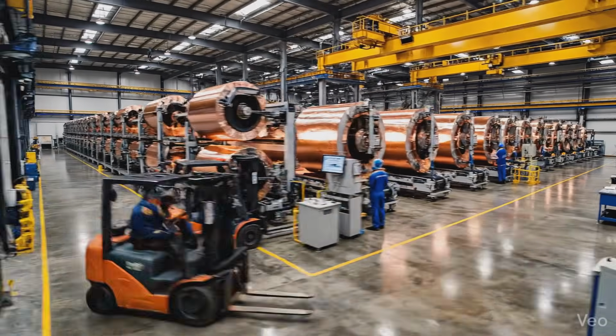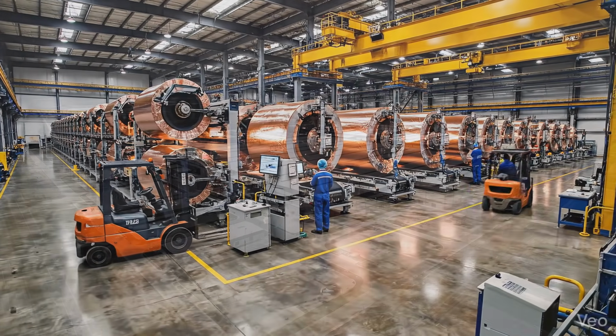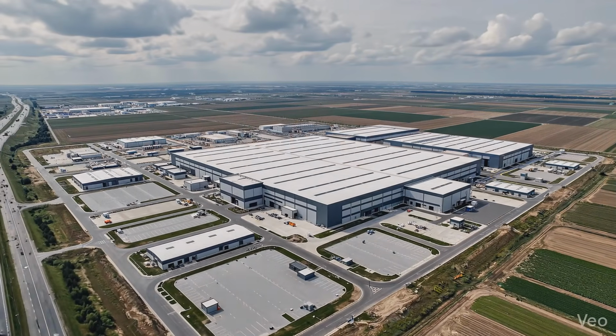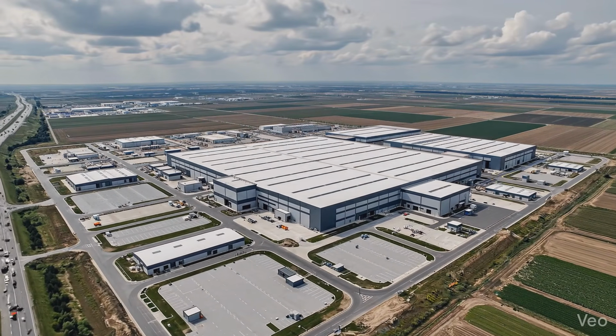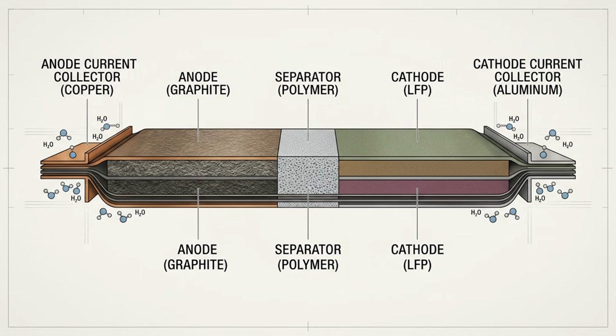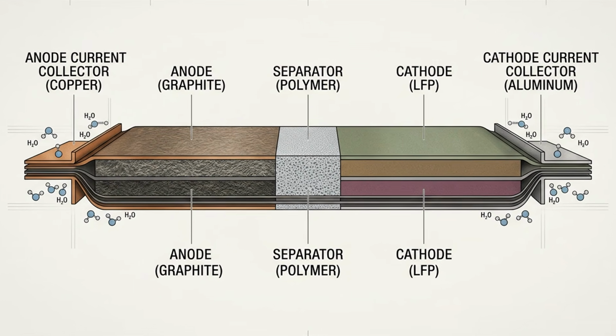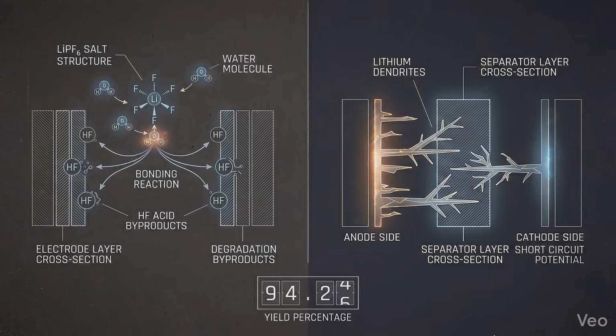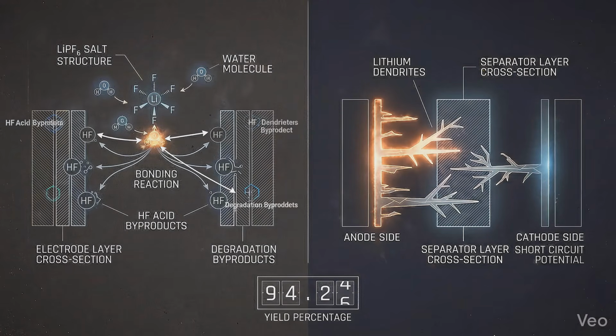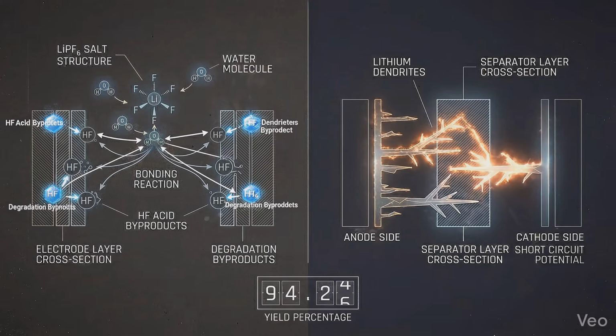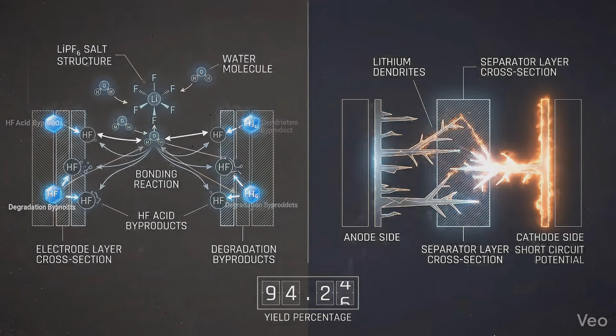There's one more constraint that rarely makes headlines, but shows up immediately when a gigafactory's construction team sits down with the budget. Lithium-ion cells are highly sensitive to moisture. Elevated humidity during electrode assembly or cell construction can trigger electrolyte degradation, specifically the hydrolysis of lithium salts like LiPF6, which produces corrosive byproducts, and can accelerate dendrite formation, increasing the risk of cell failure and reducing batch yield.